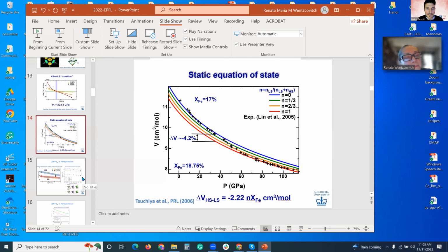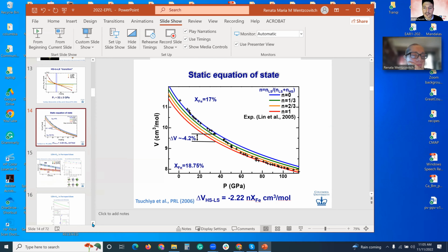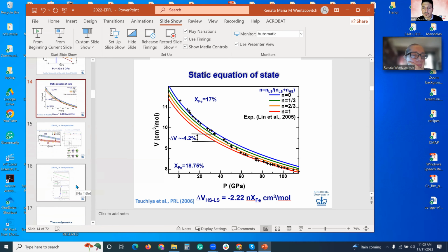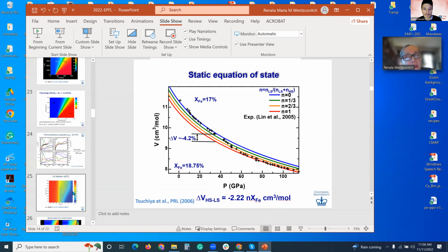Thanks. So another question that is instead more related to the high spin and low spin phases. Could you please elaborate on the interaction between iron, high spin and low spin? For example, for a supercell that includes both high spin and low spin iron, does the high spin iron have any preference for its neighbors? Which kind of neighbor? Yes, it does. Actually, U also changes if you have two high spin irons, one with parallel or anti-parallel spins, U changes likely. Okay, the preference is for anti-parallel neighbors. When they are neighbors, that's when you have irons or second neighbors.